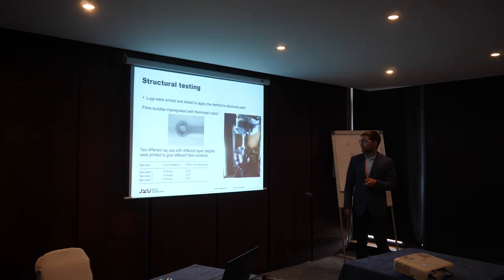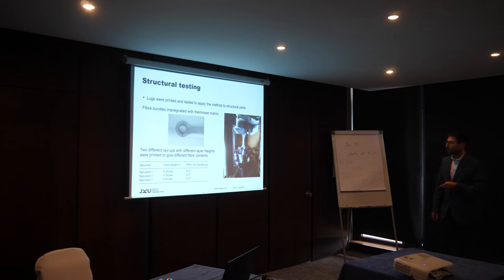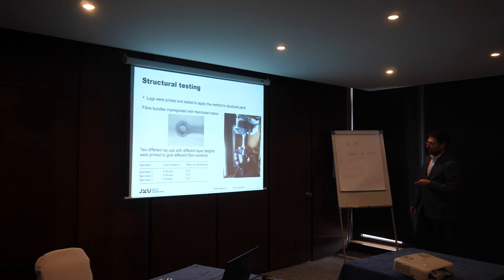This is the finished structure post-testing — you can already see the fracture. I would like to draw your attention to our test machine: we put the lug end of our part into a fixed jig where a pin prevents any displacement, and then we pull with a hydraulic cylinder.